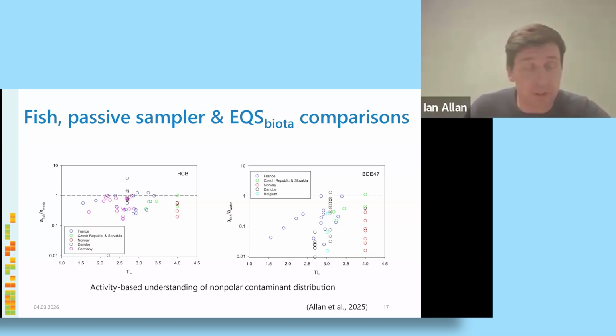And then a number that's below 1 is telling you that the fish is not as contaminated as the water is. And that's very interesting because for hexachlorobenzene, all the data is sitting not so far from the one-to-one relationship. There's a few numbers that are above 1, but most of the data points are below or at around 1. I forgot to mention the x-axis is the trophic level of the fish that was sampled, either measured or assumed. And then for BDE47, the picture is even more striking because actually the concentrations in fish could be as low as 2 orders of magnitude below the concentration level or the activity level in the water.